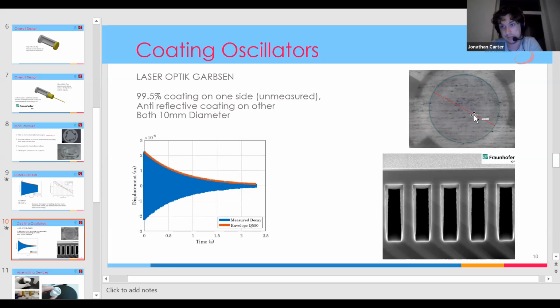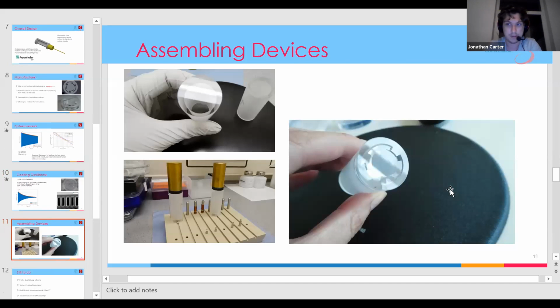Thankfully, part of the collaboration with the IOF is that they're working on resonant waveguide gratings. These are microstructures that, through interference, allow very high reflectivity whilst not adding any layer on top. It's just a microstructure, which should in principle preserve the high quality factor of the fused silica. So we're currently working on a design that has this incorporated as its mirror reflectivity as well, and that will be produced in the coming months.